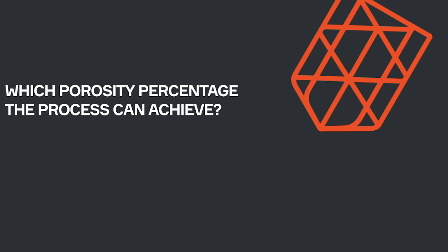Which porosity percentage can the process achieve? That's a good question. In certain regimes, we can achieve a porosity of less than 2% without any post consolidation and post treatment,